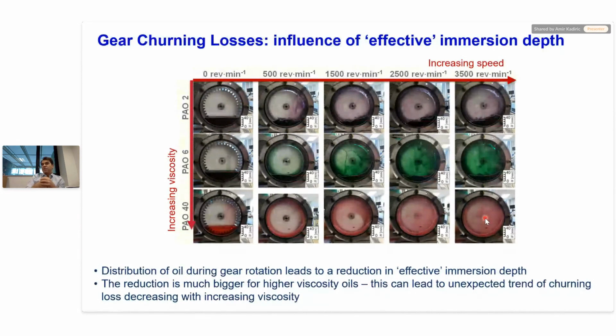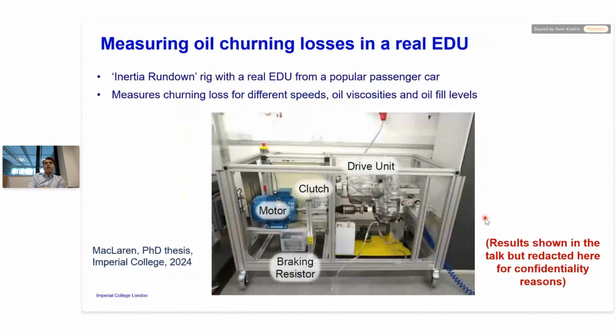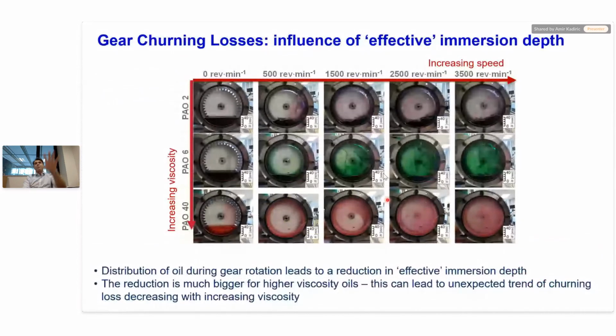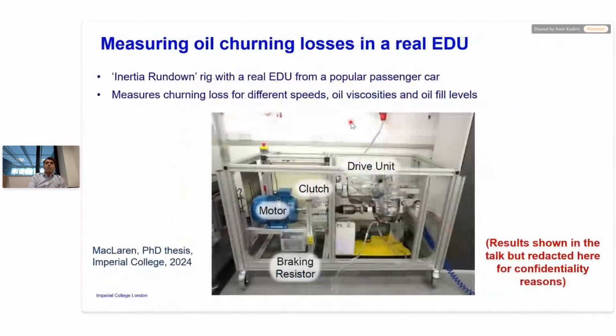Now you might think, well, this is specific to this rig, and indeed the absolute values of churning loss are specific to this rig. But we actually did it in a real electric drive unit. So here's a real electric drive unit. The way we do this is we spin up this gear to a certain speed, and then we disconnect it and let it slow down due to this churning loss, the drag of oil. And then from the speed-time graph, we get a churning torque. So it's called the inertia rundown method. And we did the same method here.